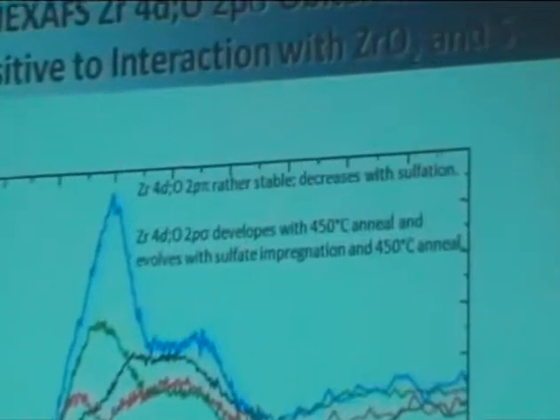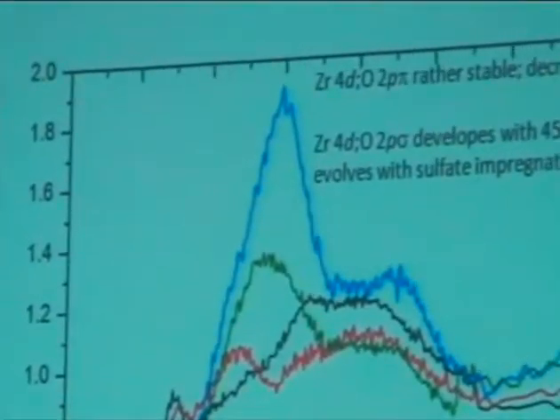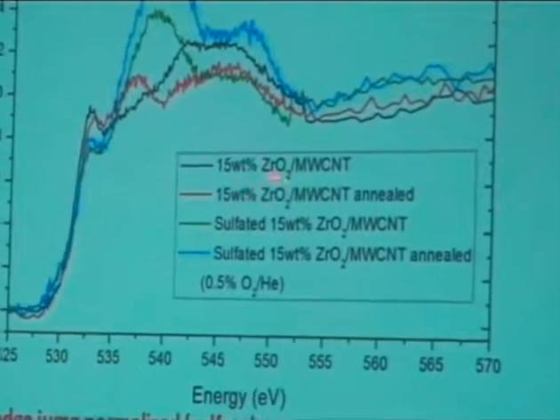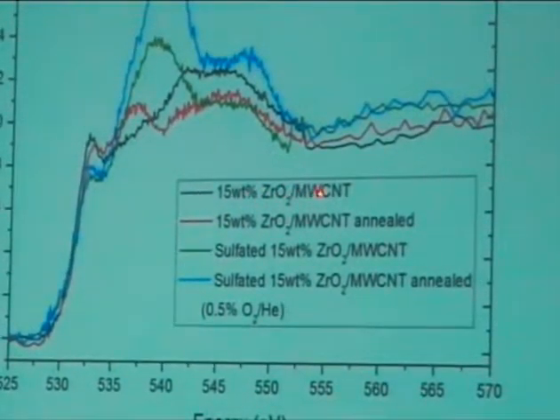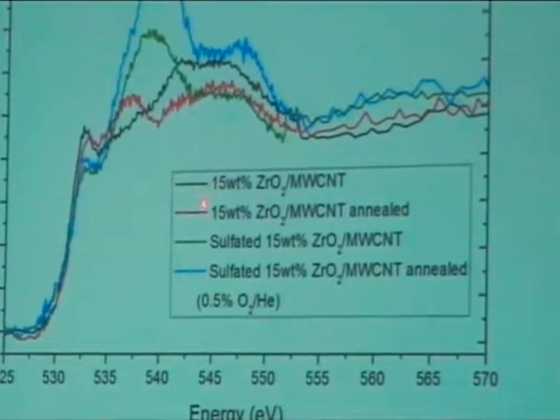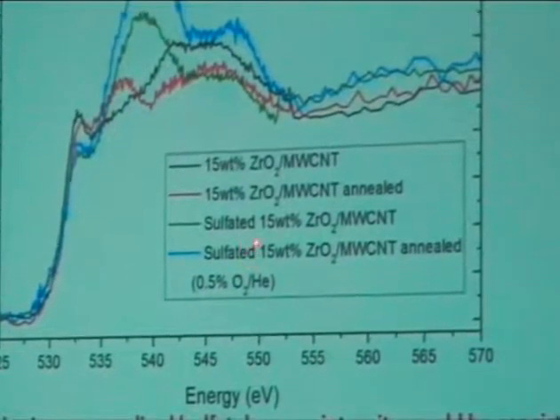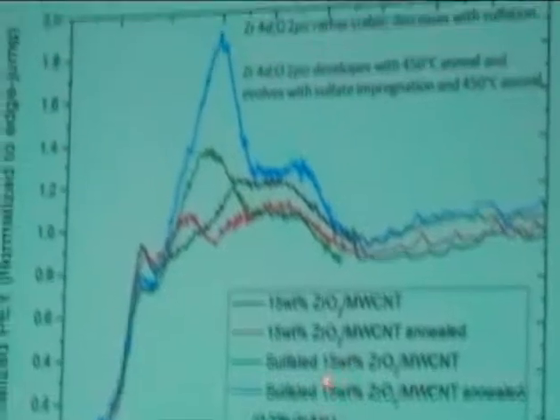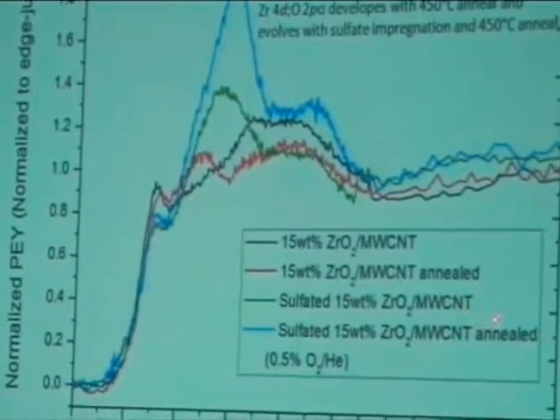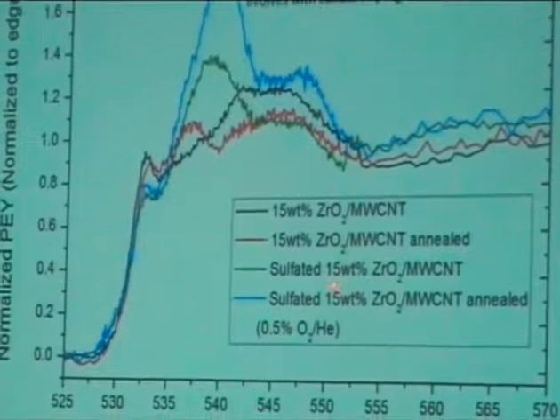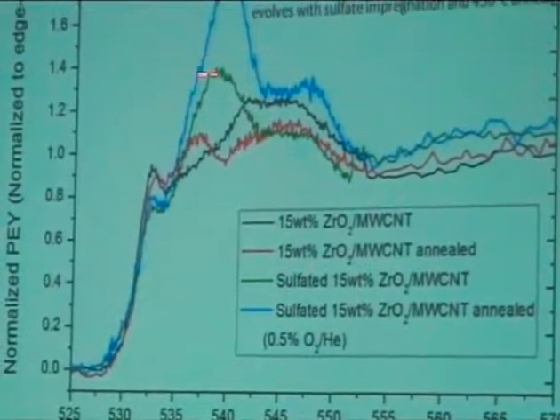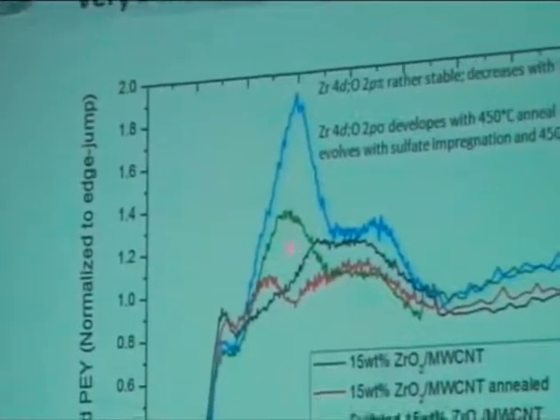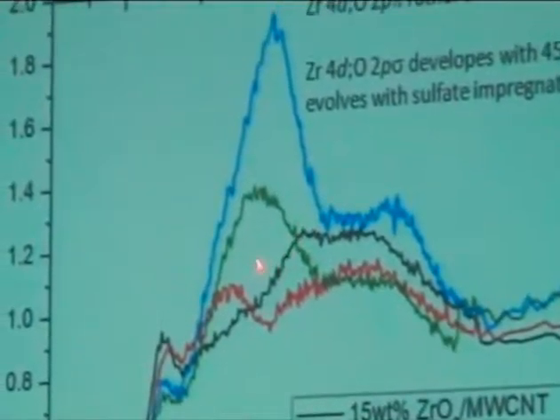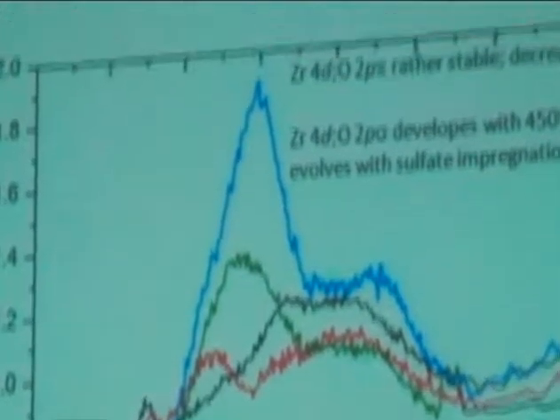And here, what I'm showing you is a case where we're comparing the impregnated 15 weight percent and then after annealing, that's the black, the red, and then we're looking at the sulfated 15 weight percent and then after annealing. And as on one of the slides I skipped, what I pointed out was that this peak is assigned to sulfate, and that when you anneal it, even though the amount of sulfur is being decreased, some of it's being decomposed and removed, the intensity goes up.